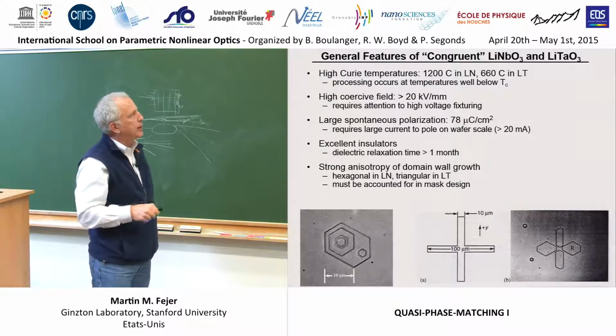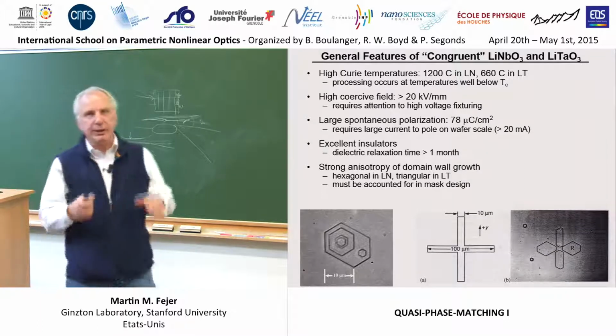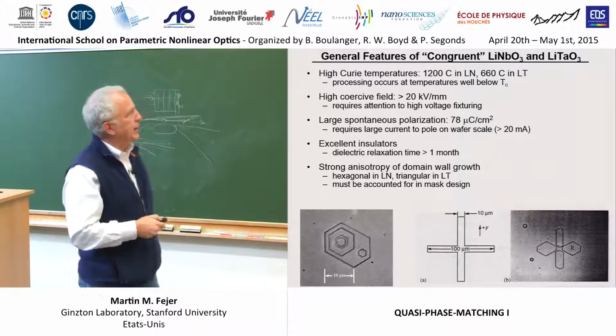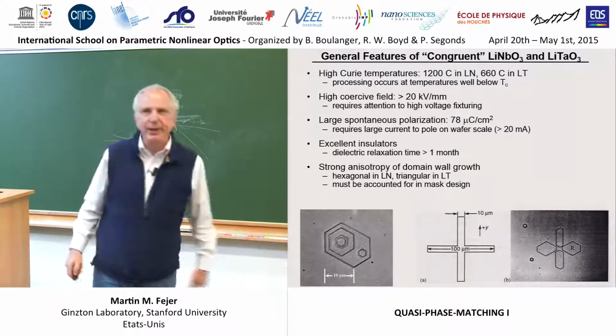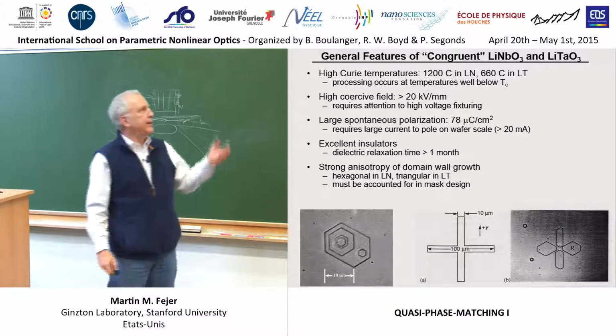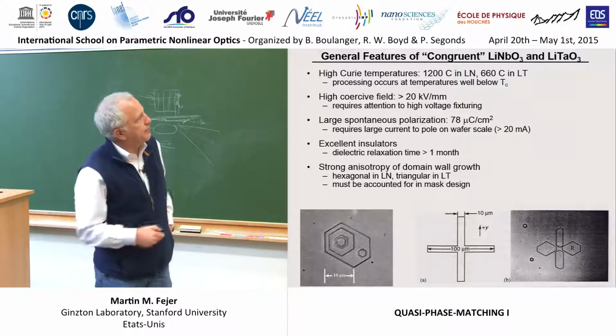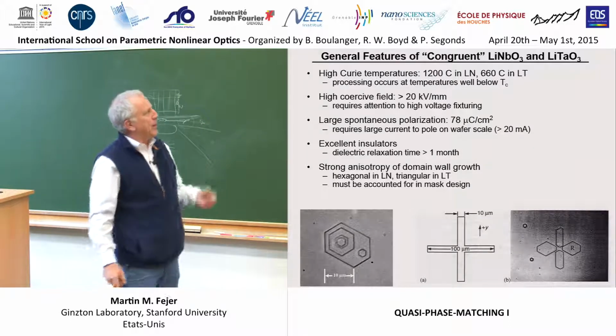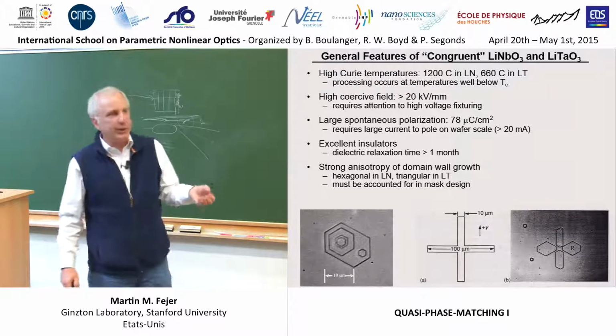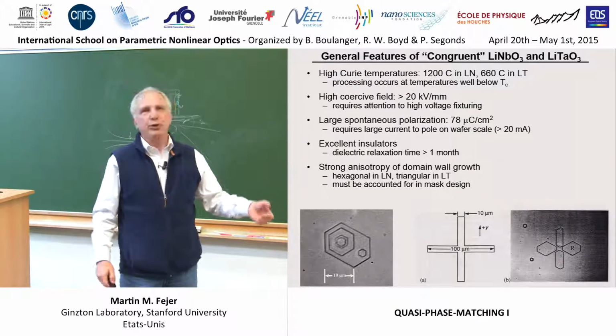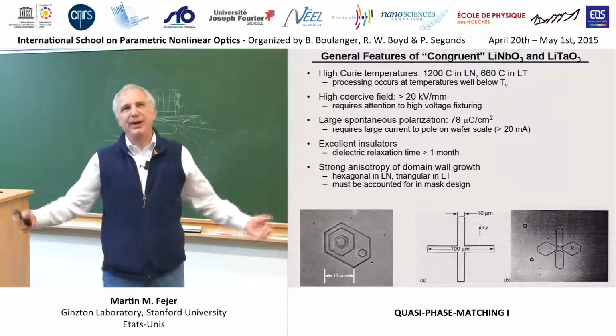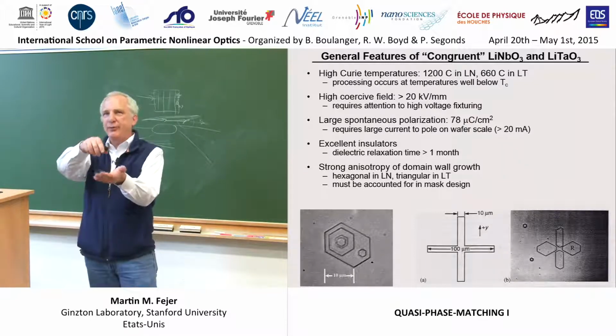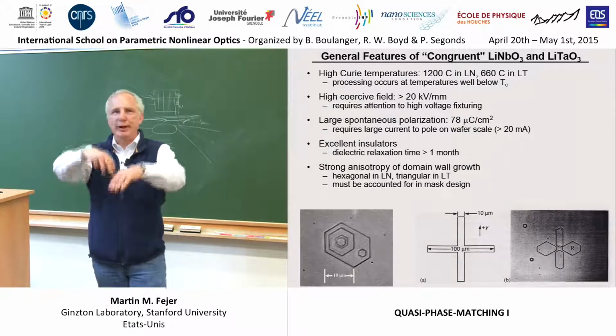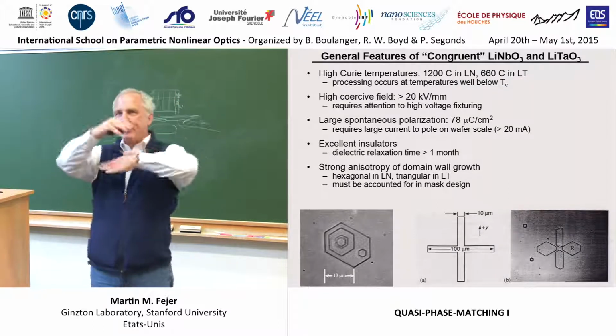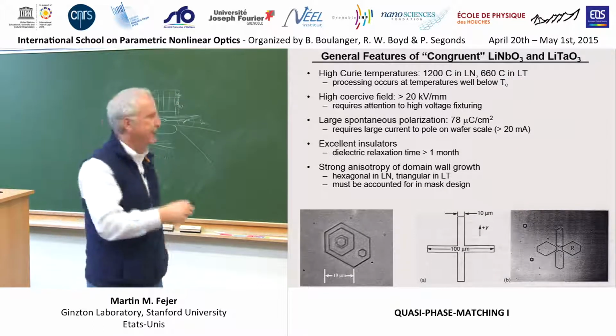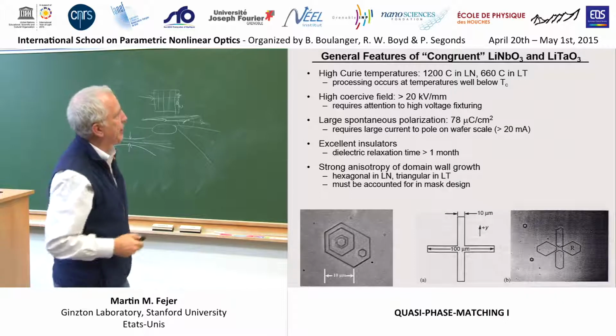There is a large spontaneous electric dipole moment. Maybe 78 microcoulombs per square centimeter doesn't mean much to you, but it's huge. If you heat up one of these crystals and grab it with a pair of tweezers, you'll get a spark. In fact, you can spontaneously get enough electric field from the pyroelectric effect that you'll break down air. So these dipole effects are very strong in these materials, if that number doesn't mean anything to you.